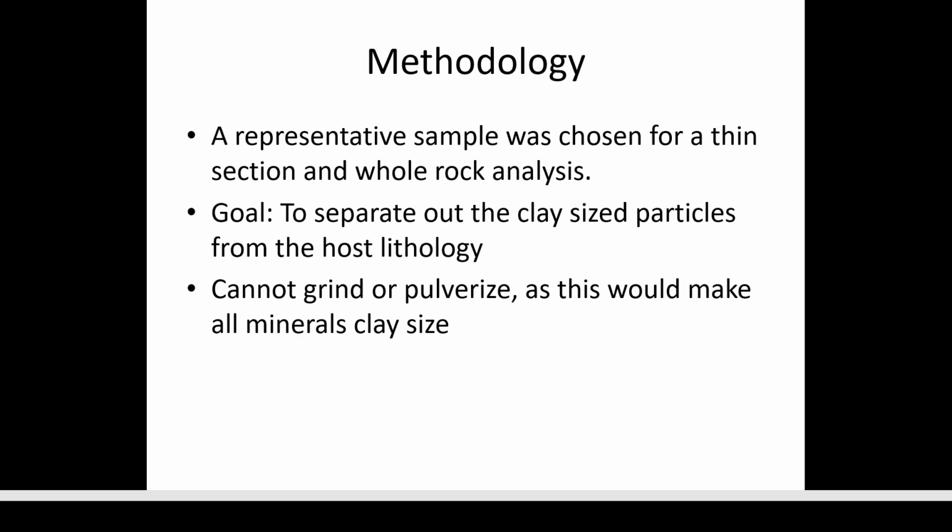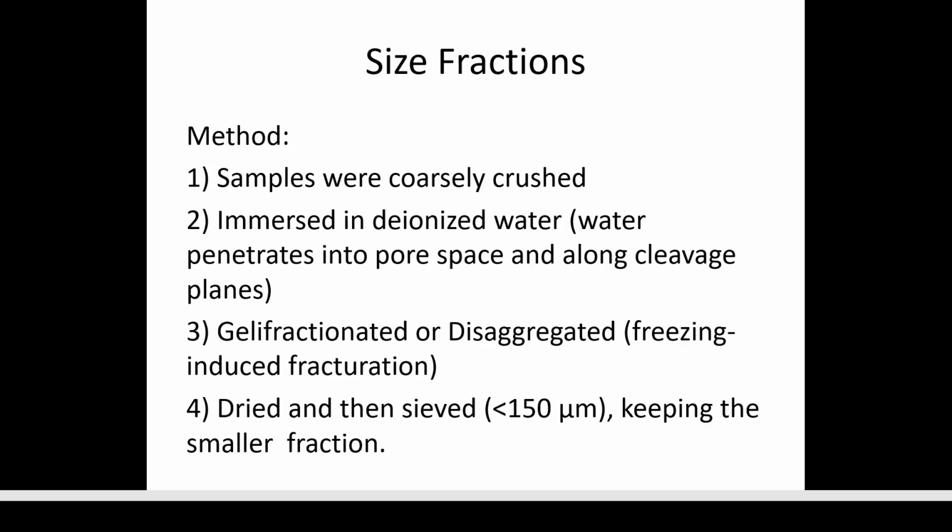To be able to do this, we cannot grind or pulverize the sample because this would make everything into the small clay-sized fraction that we want. So what we have to do is separate the sample along the different cleavage planes to then be able to extract only the size particles that we want to study.